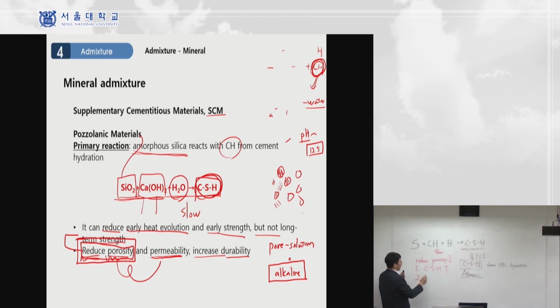Number two is it consumes calcium hydroxide. Because the main role of calcium hydroxide is to maintain the high pH of the pore solution. It does not provide strength, for example. It does not have much impact on the volumetric contribution to the composite. So by changing this calcium hydroxide to the calcium silicate hydrate, this is the main chemical pathway, right? CH to CSH. So we can also reduce the porosity.